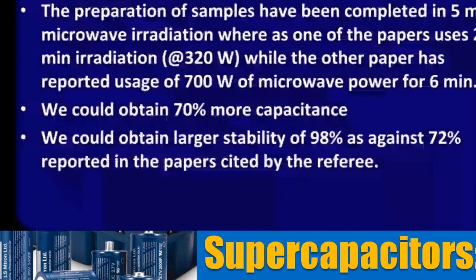In the morning you take it with full charge, come back home and again you charge it. And this is what we call cyclic stability. Because of the nature of the electrode, as you keep on charging and discharging, the capacity will be lost. And you see that the microwave irradiated material, or material produced through microwave irradiation, gave us a material where the loss is just 2% after thousands of cycles.